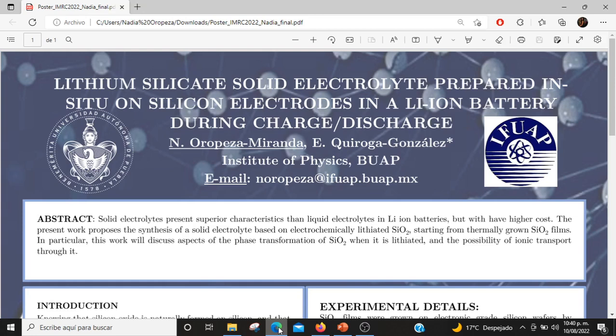It's well known solid electrolytes present superior characteristics than liquid electrolytes in Li-ion batteries, but with higher cost. The present work proposed the synthesis of a solid electrolyte based on electrochemical lithiated silicon oxide, starting from thermally grown silicon oxide films. In particular, this work will discuss aspects of the phase transformation of silicon oxide when it is lithiated and the possibility of ionic transport through it.